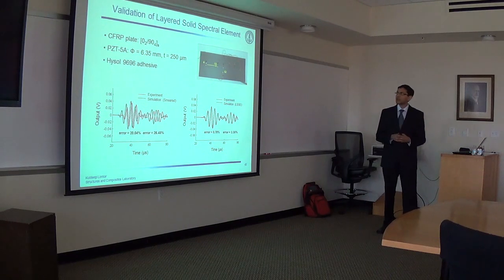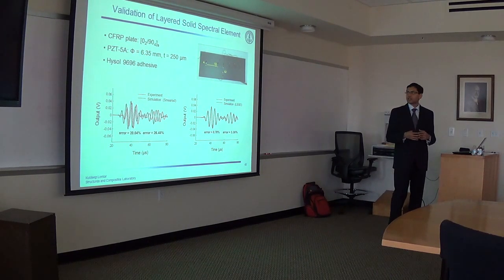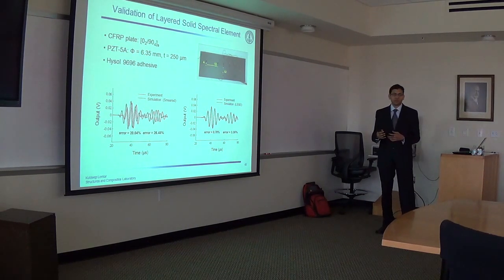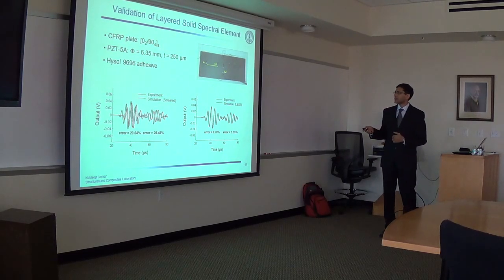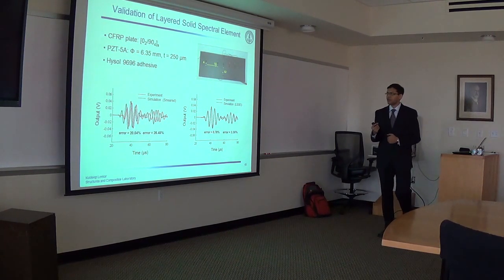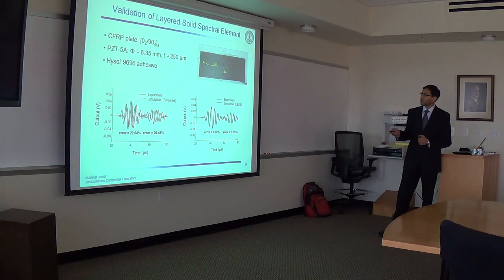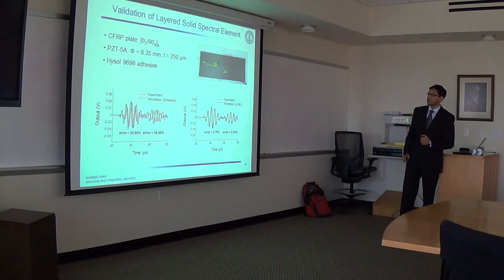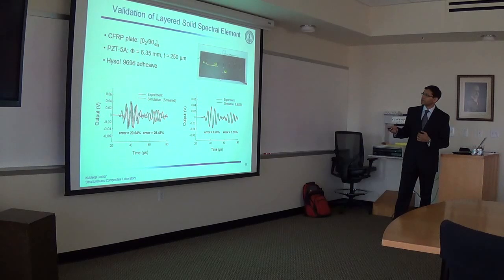So let me show you the validation for the layered solid spectral element. To validate the layered solid spectral element, simulations and experiments were carried out for a composite plate with layup 0 to 90 symmetric. Again, piezoelectric sensors with quarter-inch diameter and 250 micron thickness were mounted on the surface using Hysol 9696 adhesive. The voltage input was given to actuator A, and signals were recorded at sensors S1 and S2.